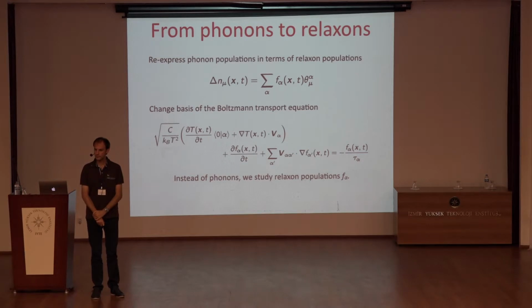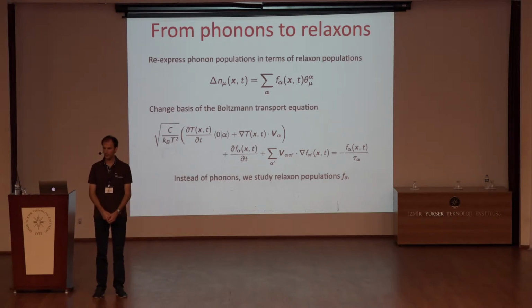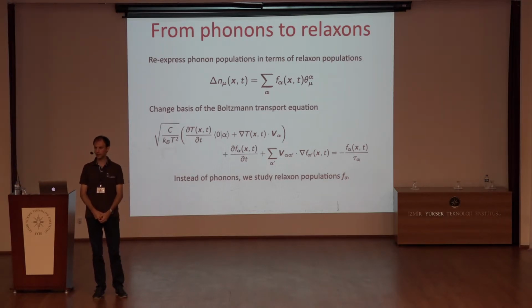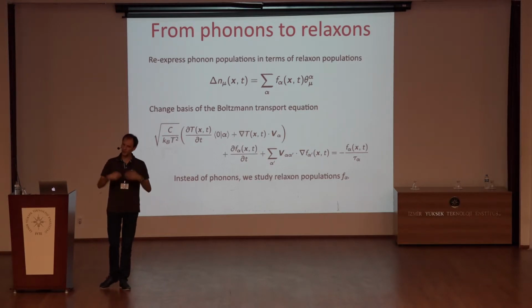So one question I have is about the diagonalization process. Is there any aspect of that matrix that is inherently temperature dependent? Yes. Okay, so does that mean your basis changes at every temperature? Yeah, as a function of the temperature. I see. So each different temperature point requires a recalculation of the diagonalization procedure, and therefore a different basis set.